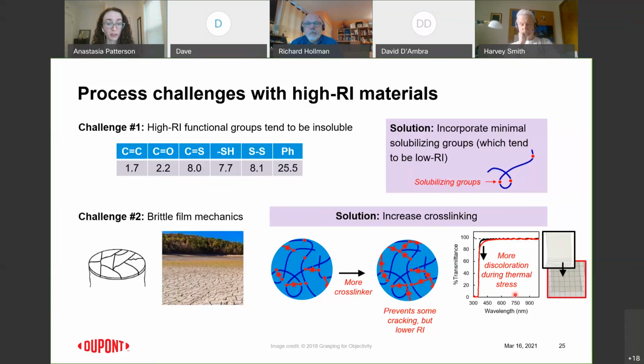And so the second challenge we mostly fixed by including much more crosslinker in the film and making a stronger network. But we noticed in collaboration with our customer that no matter how much crosslinker we added, there was still cracking, and it really shouldn't be there based on the amount of crosslinker we added. So there was something else going on.